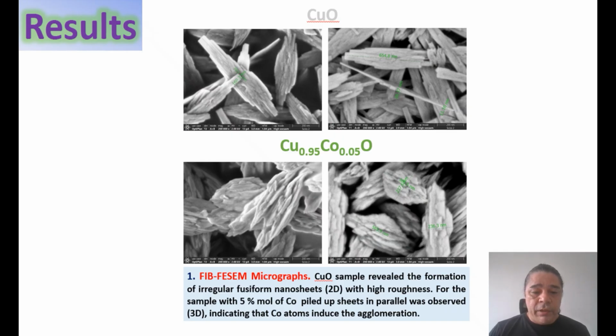Results. Field emission scanning electron microscopy. The copper oxide sample revealed the formation of irregular fusiform nanosheets with a 2D structure. For the sample with higher cobalt concentration, we observe these nanosheets piled up in parallel, evidencing a 3D structure, indicating that cobalt atoms induce the agglomeration.